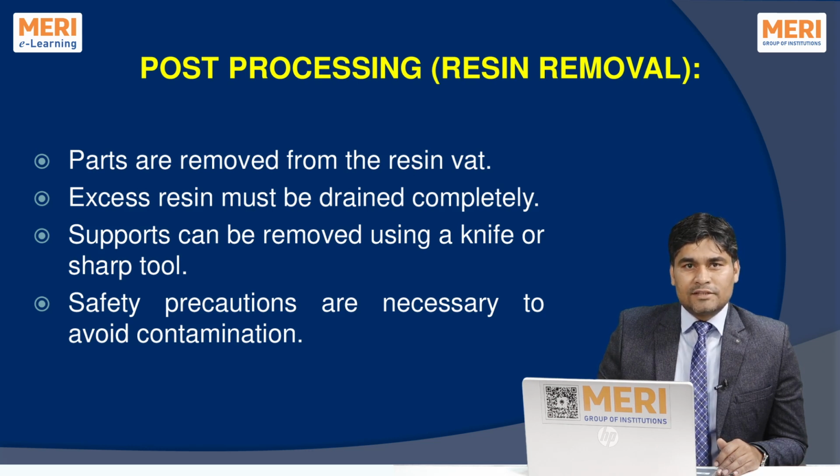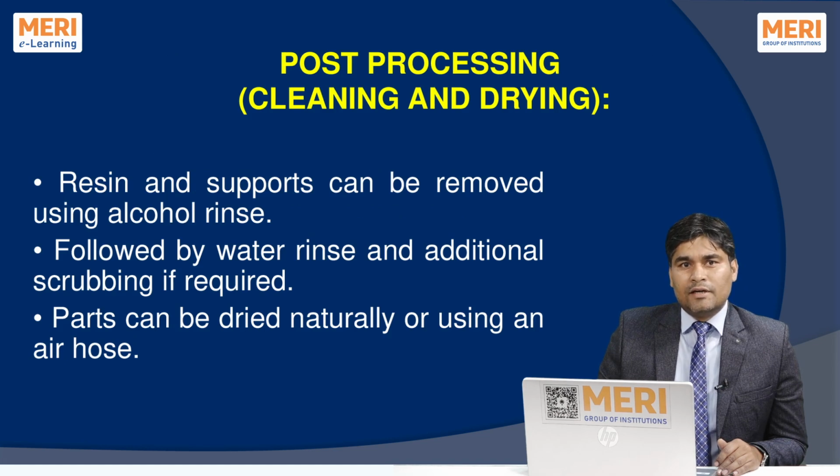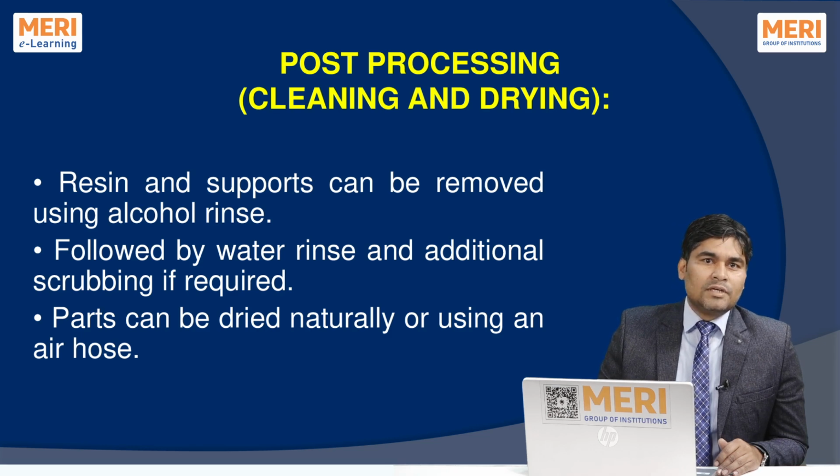While performing this step, proper safety precautions must be followed to avoid skin contact and contamination, as photopolymer resins can be harmful. After removing the printed part, any remaining resin and support residues are usually cleaned using an alcohol rinse, which helps dissolve and remove uncured resin from the surface. This is generally followed by a water rinse and gentle scrubbing if required to ensure that the part is completely clean.